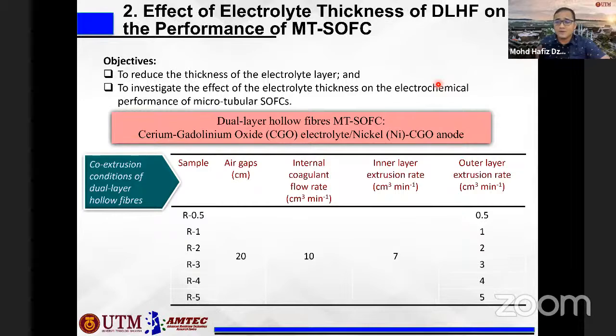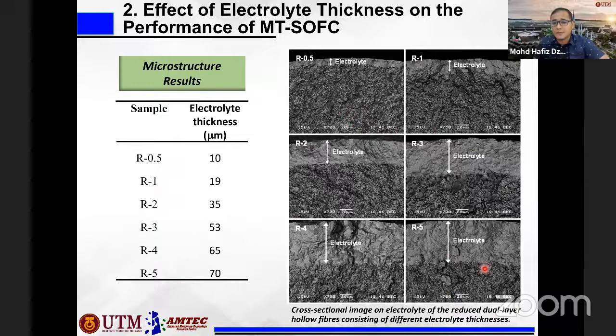The good thing about the co-extrusion process is that we can adjust the structure and the dimensions of the fuel cell accordingly. So if we want to reduce the thickness of the electrolyte, we can alter the extrusion rate from 5 down to 0.5 ml per minute. By varying the outer layer extrusion rate, we can produce different electrolyte thicknesses, from 10 micron up to 70 micron.